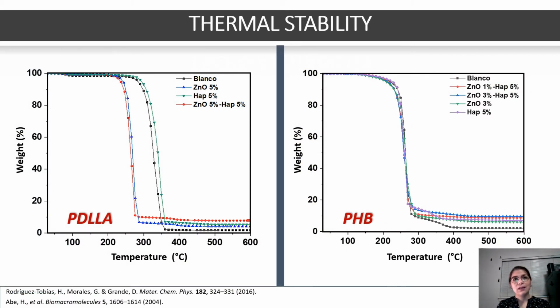Regarding the thermal stability, a decrease comparable to that presented by the system obtained at 5% of zinc oxide was observed in the ternary system of PDLLA. As can be seen, despite the fact that hydroxyapatite slightly increased the thermal stability of fibers, the zinc oxide in the ternary system completely counteracts the effect of hydroxyapatite, producing a degradation equivalent to the system formulated only with 5% of zinc oxide. Different publications attribute this behavior to the fact that zinc oxide promotes transesterification in the polymerization reactions of PLA.